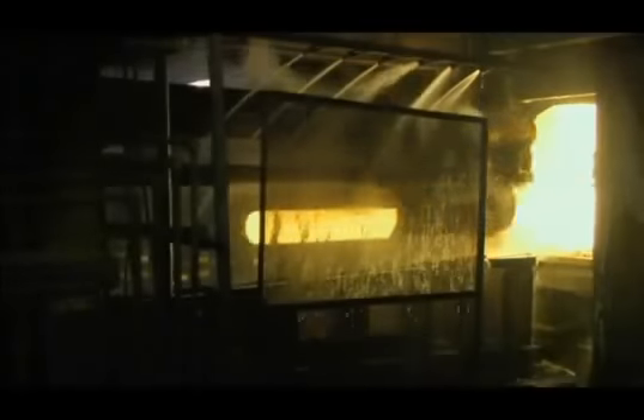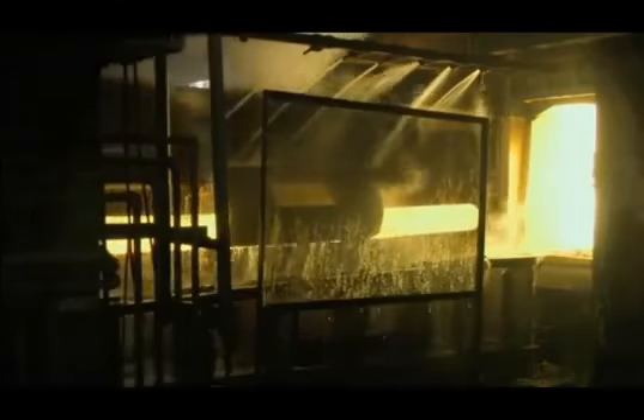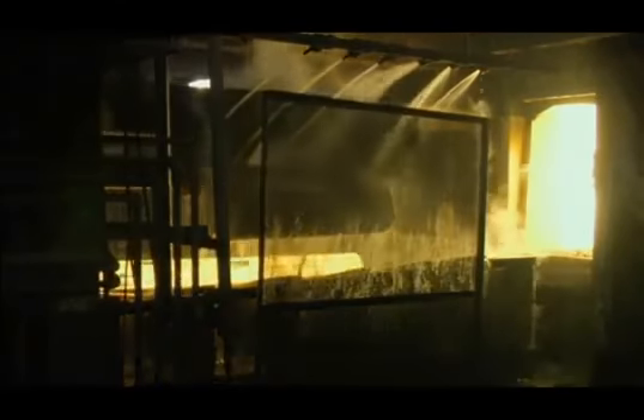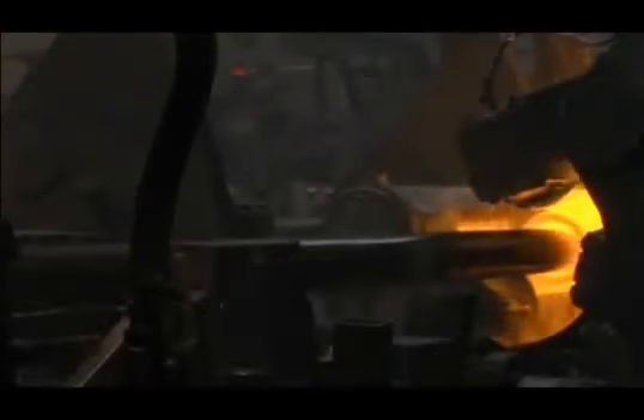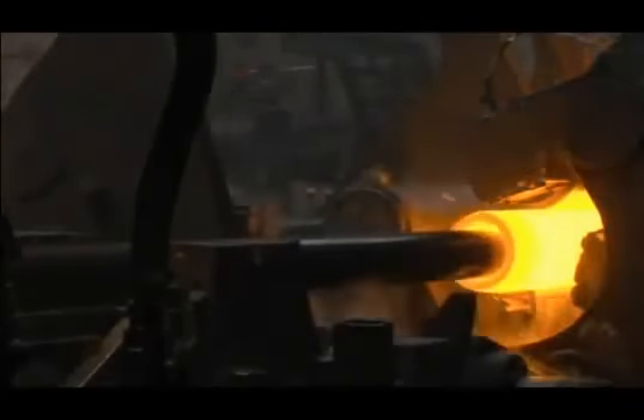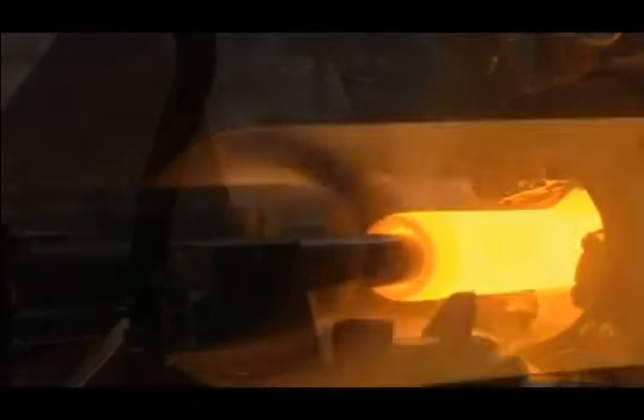Round billets from one of our rolling mills are reheated in a rotary furnace. The billets travel once around the furnace and emerge at the appropriate temperature for piercing. The billets are transferred to the piercing mill, where they are drawn by 2 rotating drive rolls over a bullet-shaped piercing plug. This rotary forging process works the metal from the inside and the outside, creating more uniform grain structure.